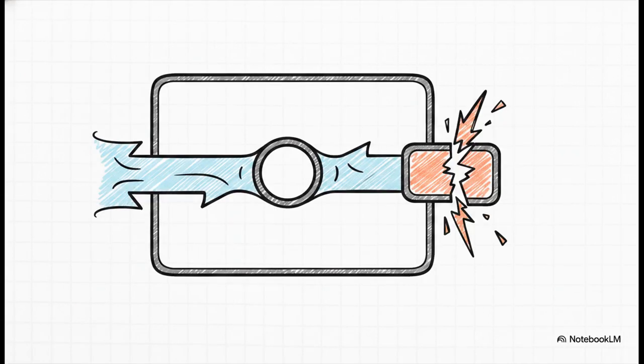So the crucial point here is managing your weld lines. A weld line forms inside the mold wherever two flows of molten plastic meet and knit back together. Say, for instance, after flowing around a hole in the part. This knit line is inherently weak. The tensile strength right at that line drops to like 75 to 85% of the solid bulk material. If you place a snap fit hinge directly on a weld line, the cyclic strain is going to cause a massive fatigue failure way before the solid material would ever actually break. Always double-check your gate locations so you keep those flow lines far away from your dynamic snaps.